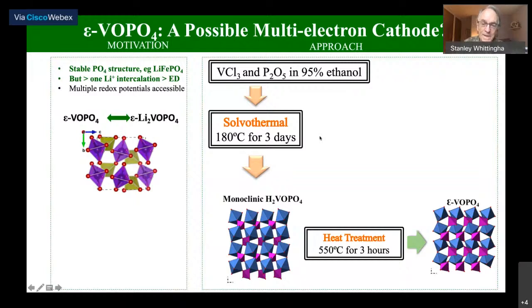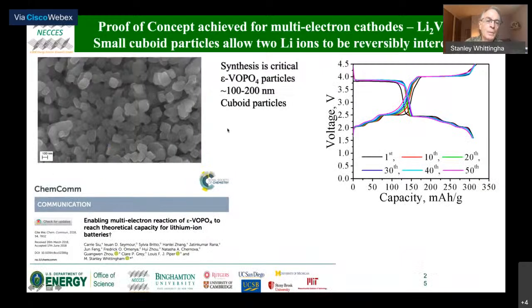I think 1 day is enough, but 3 days is a nice weekend. If you do that, then you make the hydrogen analog of this material. A low temperature heat treatment gets rid of the protons, or you can chemically remove these protons or electrochemically at room temperature. So make this nice structure. And what we form are these nice cuboids, about 100 nanometer in size, all uniform.